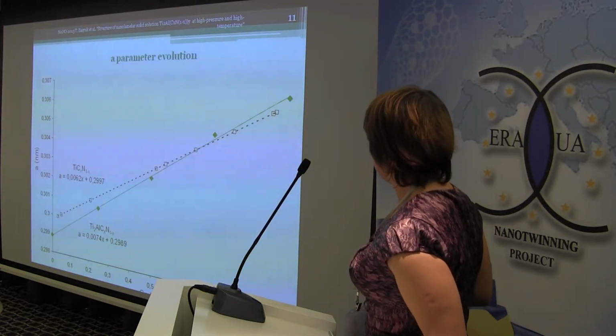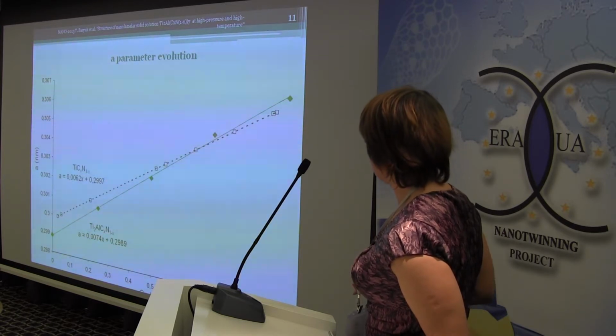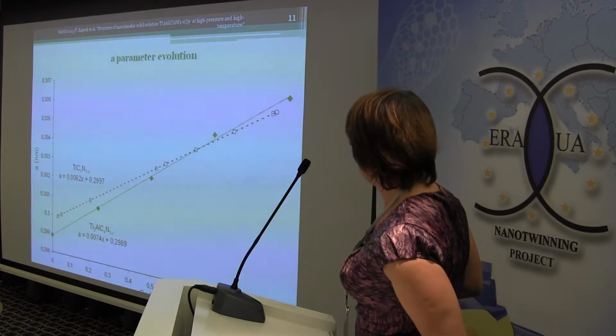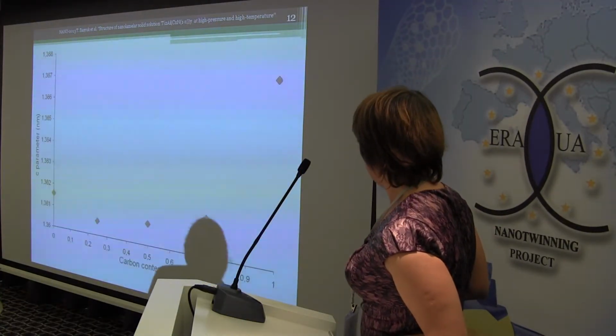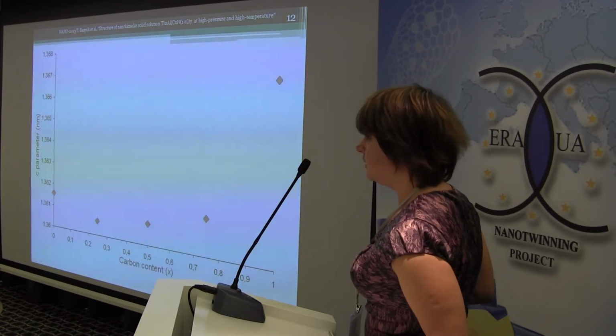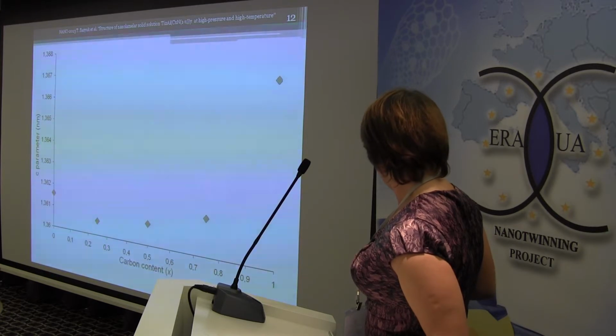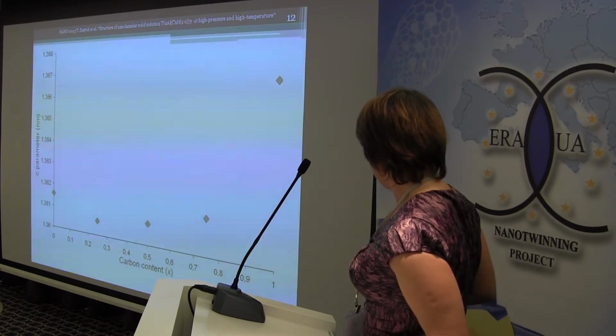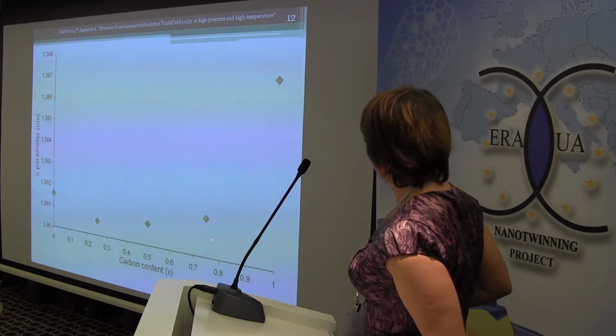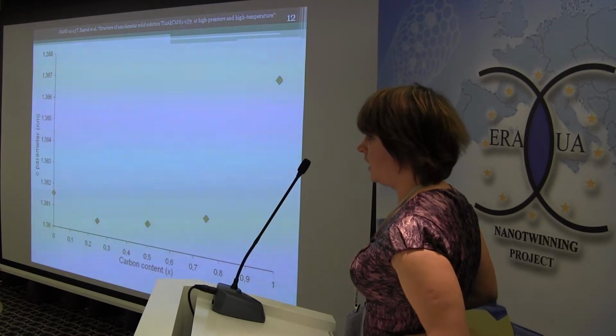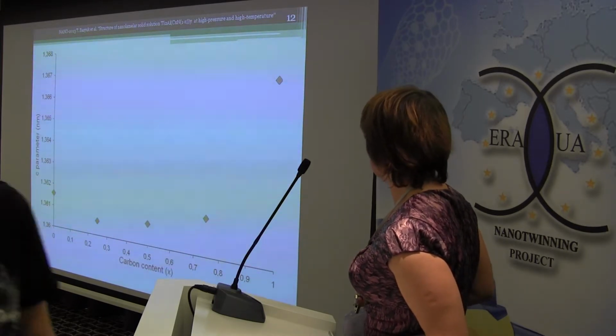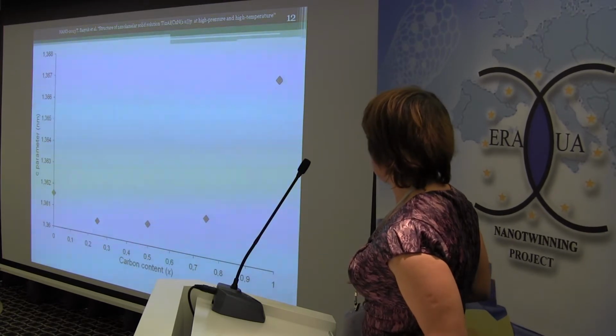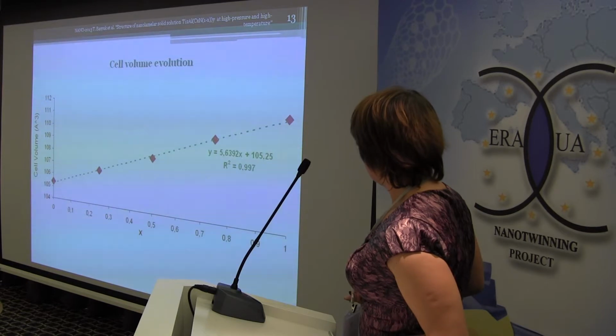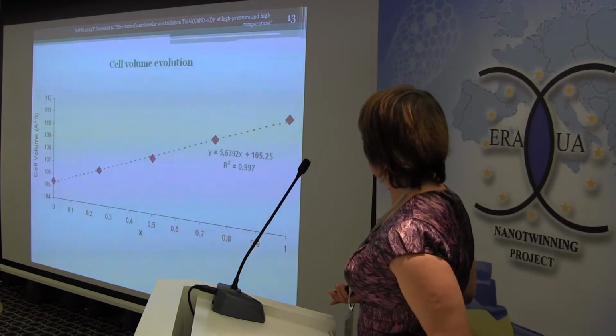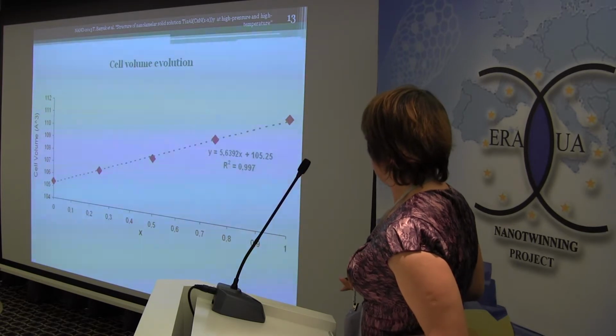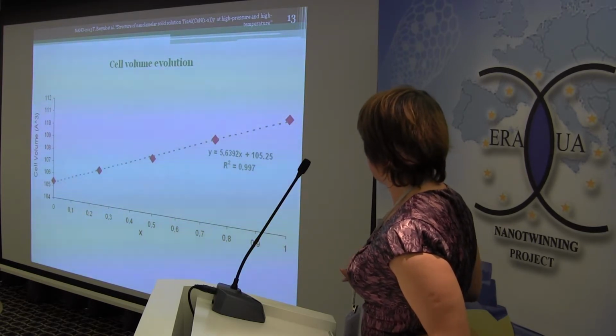Also, we estimated the structure parameters. The A parameter linearly increases with increasing carbon content, but for the C parameter we discovered some phenomenon, because the value of the C parameter for our carbonitride solid solutions is lower than for the pure nitrides and carbides. But the cell volume depends linearly on the carbon content, following Vegard's law.